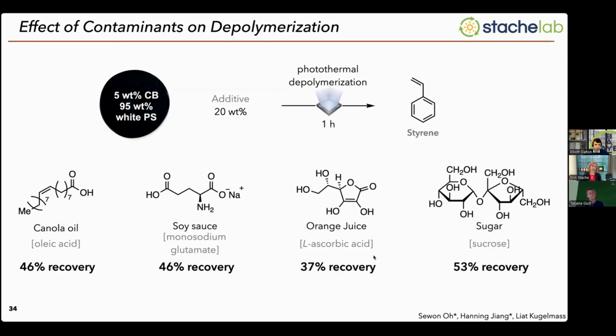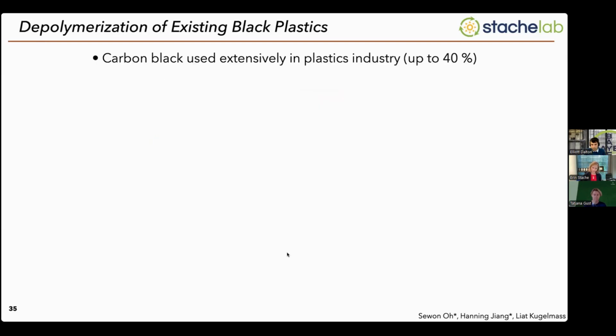And what we found is that in all cases, we see almost comparable depolymerization efficiency to the standard reaction conditions. We do see a little bit of loss of efficiency with ascorbic acid, but this is a known radical scavenger, and so that kind of makes sense. But because it is a purely thermal process, these different additives are not interfering with catalysis here.